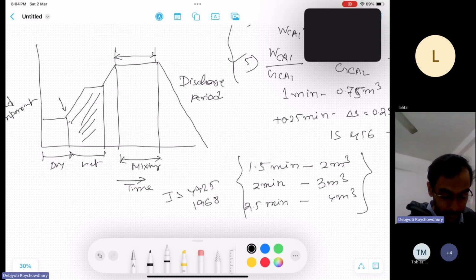Increasing the mixing time results in more uniform distribution of hydrated products, and higher compressive strength may result. However, if you keep on extending the mixing process, with the rolling action, because there is a tilting device also, the machine where the materials get mixed, due to the crushing and abrasion, the aggregate also gets crushed and the fine aggregate becomes more, and it may not give you the desired strength. So prolonged mixing may not increase the strength proportionally and may result in a decrease in some cases. So you have to be careful.